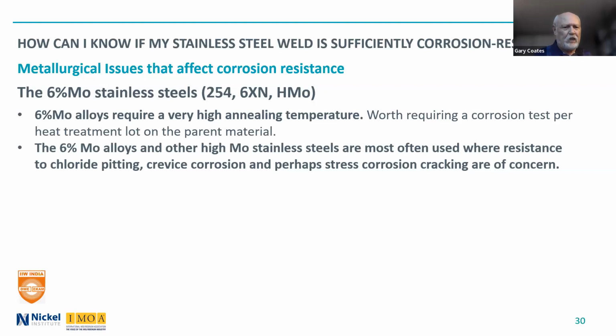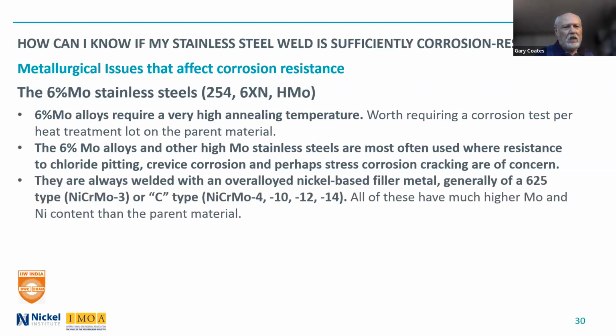They're used in more severe environments, and so those defects that we talked about in the physical part are all extremely important. Now, all these 6 moly stainless steels are welded with an overalloyed nickel-based filler metal of the 625 type or the C type, and there are variations on the C type. All of these have much higher molybdenum content and nickel content than the parent material. They have proven to be the proper ones to use for welding.